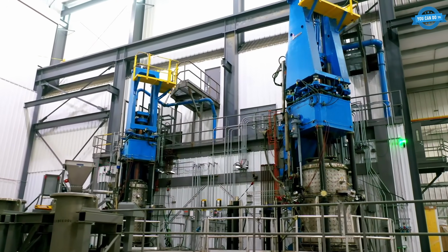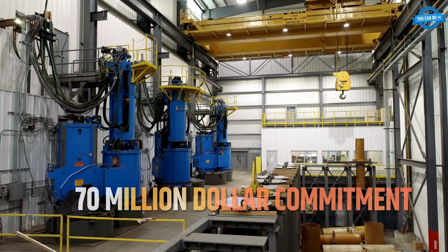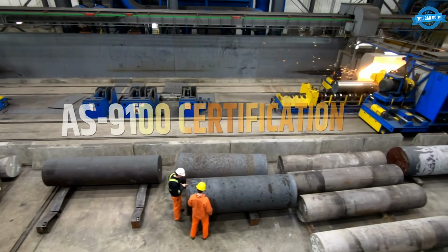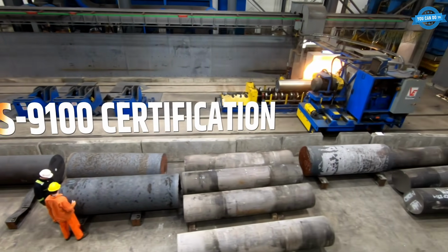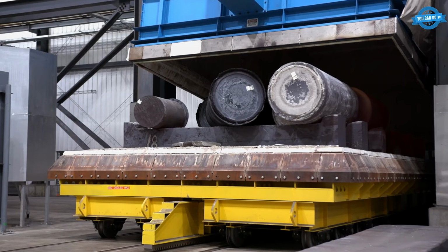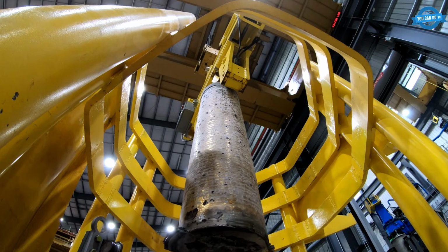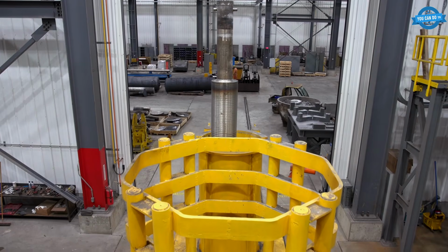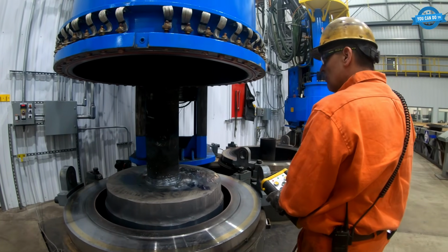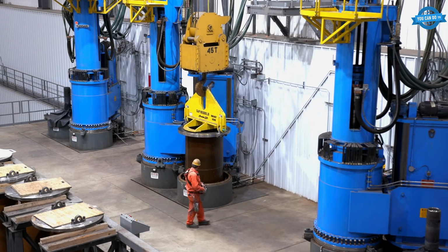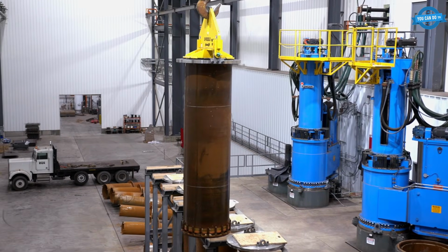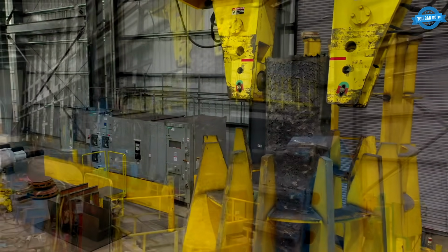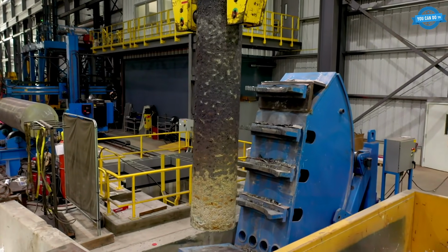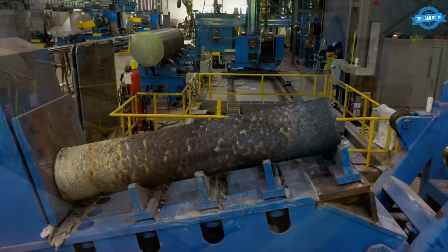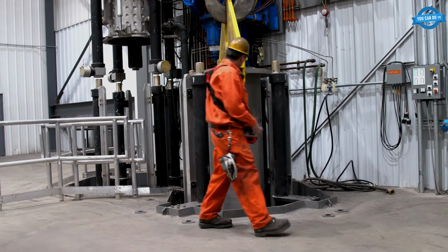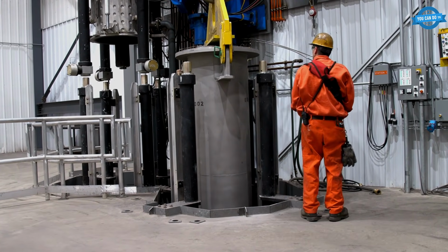The investment topped $70 million and earned aerospace-grade AS9100 certification because forging customers cannot afford a hidden inclusion to be lengthened into a future fatigue crack. In vacuum arc remelting, an electrode is melted drop by drop, under vacuum, a process that takes up to 48 hours and pulls down dissolved gas, segregation, inclusion content, porosity, and internal cavities.